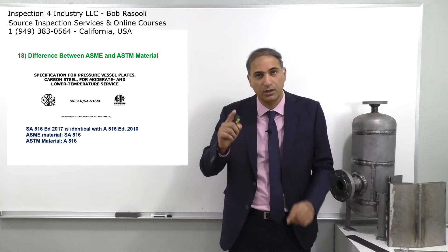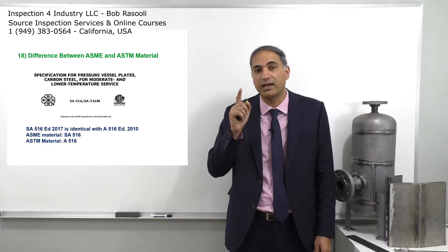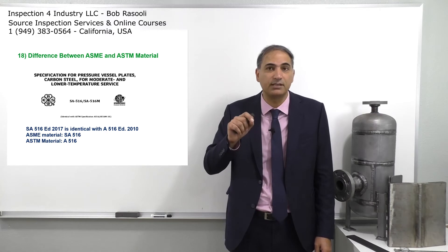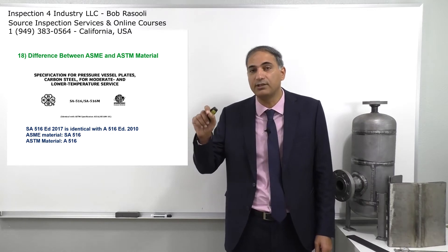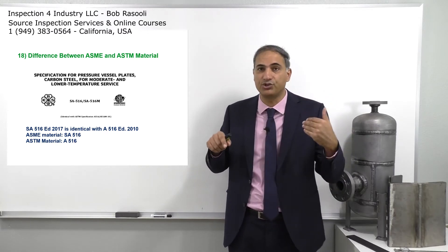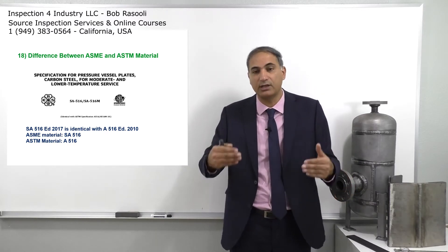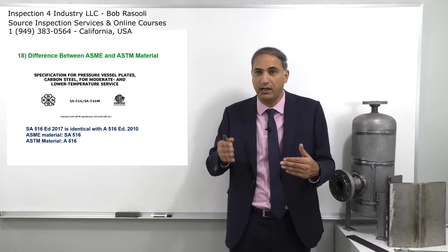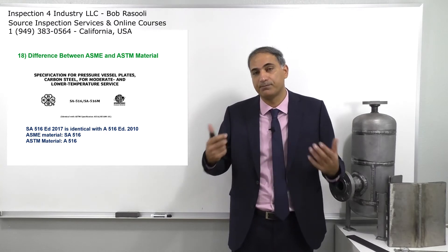This is a very important point: the 2017 edition of ASME Section 2 Part A for SA-516 grade 70 is identical with A-516 grade 70 edition 2010. Please note that the 2017 edition of ASTM is available but it is not identical with the ASME 2017 edition. The code committee needs time to review ASTM changes and assess whether they affect pressure vessel design before adopting a new edition.